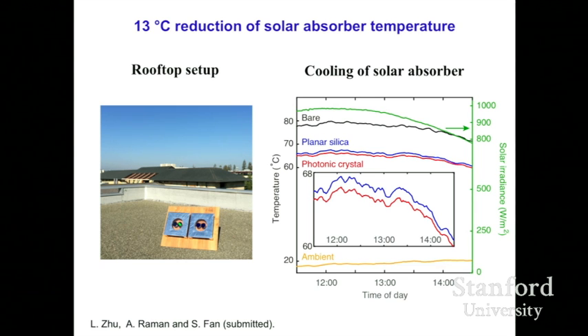And moreover, out of the three structures, the photonic crystal structure has a consistently lower temperature compared to all the other structure due to the enhanced thermal radiation coming from the photonic crystal. So one indeed sees the possibility of significant radiative cooling for a solar absorber structure. In this experiment, we have put a polyethylene film to cut down the convection. The temperature that you have here, because the structure absorbs the sunlight, by necessity is above the ambient.